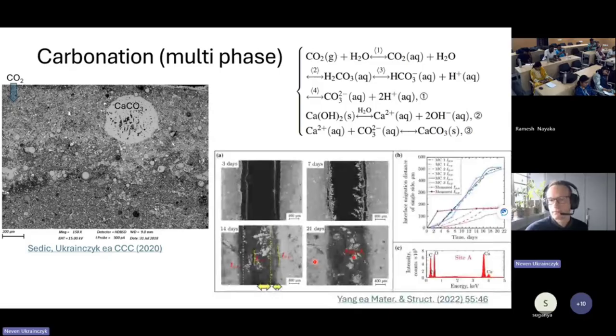So this is aggressive carbonation, and here, if you have a crack, it's another paper from a PhD student here. She used the phase field model, so sealing of the crack. It's also self-healing in this case, and then you can see with time how the crack heals. So you can see this penetration of the front, how it's moving, and how it actually seals the crack.